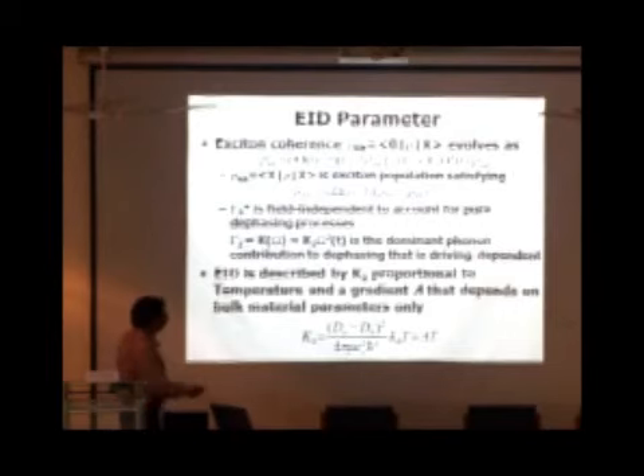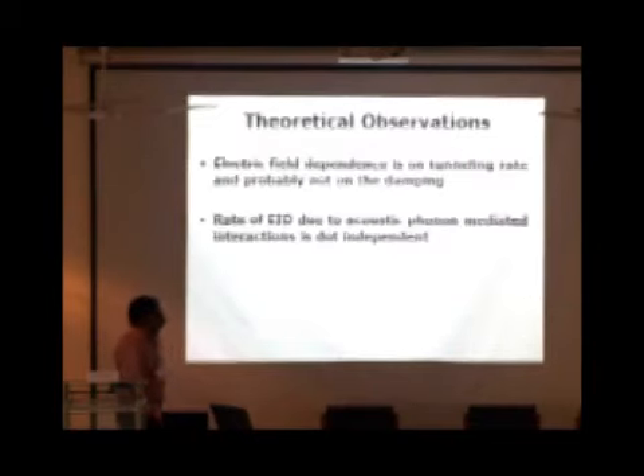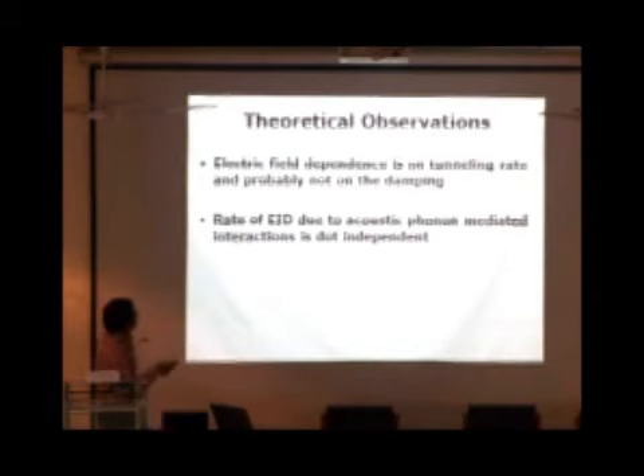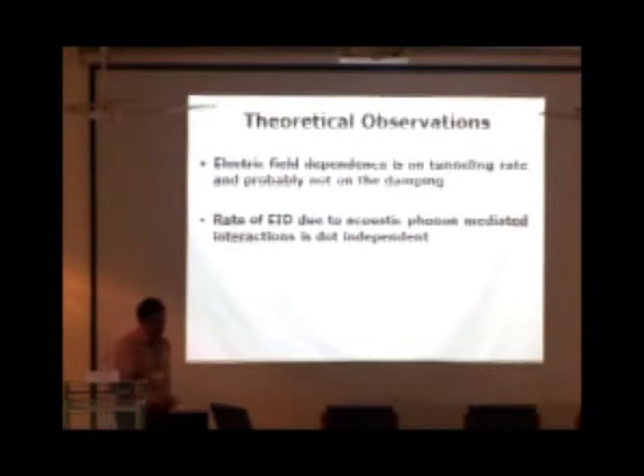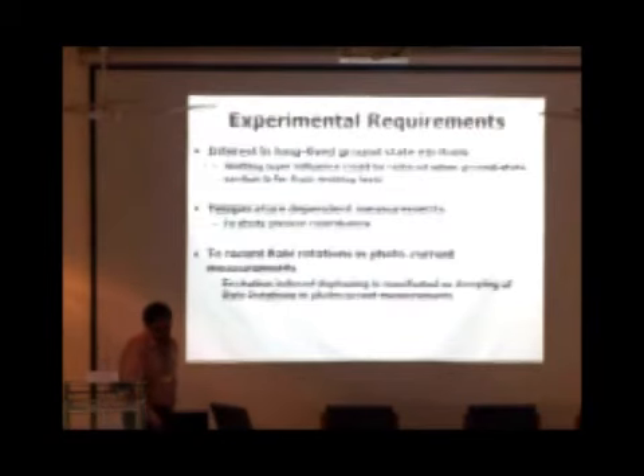So what we wanted to do is measure this K2 parameter as a function of temperature. For that we need to do electric field dependence. The theoretical observations are that electric field dependence is on the tunneling rate and probably not on the damping, and the rate of EID due to acoustic phonon mediated interactions is dot independent. So we designed our experiment to match all these things.